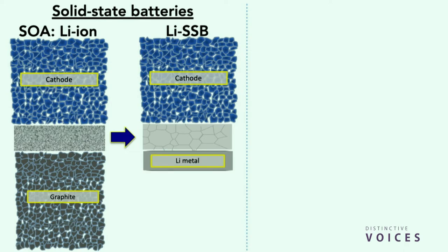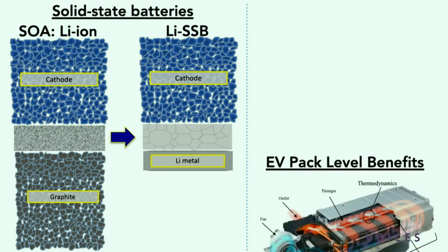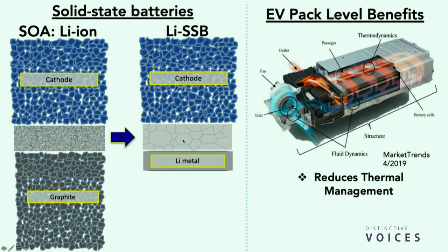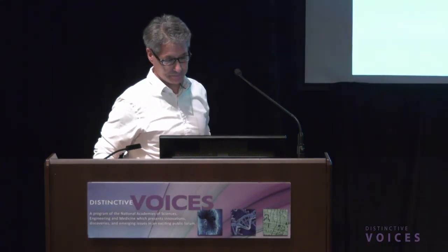So at the cell level, if one can do this, making this type of material, you can see the dramatic improvement in terms of energy density. You can reduce the volume of the cell. Another thing, though, is that you can get rid of the liquid. Right? There's no liquid in the cell. It's not combustible. And because of these materials, these ceramics, the transport of lithium ions gets exponentially better with increasing temperature. You want it to get hot. Right? So you can do away with a lot of mass, complexity, cost, and volume, the thermal management systems on EV battery packs. So if one can do away with the thermal management, you can have dramatic improvements at the pack level as well. So a lot of impetus, two good reasons to go from a liquid to a solid electrolyte.